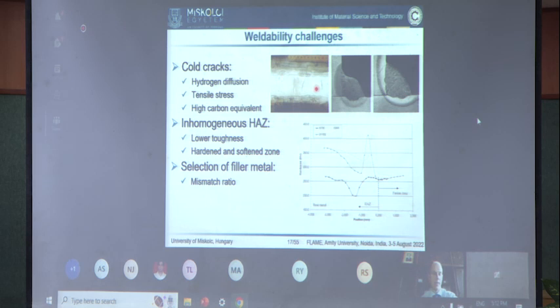These photos were taken by our industrial partners, and generally they find this kind of transversal cracks in the welds of their welded structures made from high-strength steels. Another topic is the inhomogeneous heat-affected zone, where the toughness is significantly reduced compared to the base material. Furthermore, hardened and softened zones, as you can see in this graph, are also located in the heat-affected zone, depending on the distance from the fusion line.